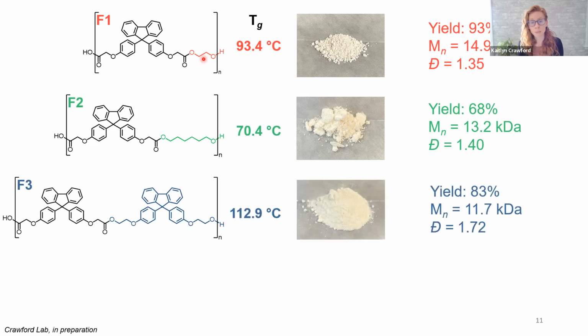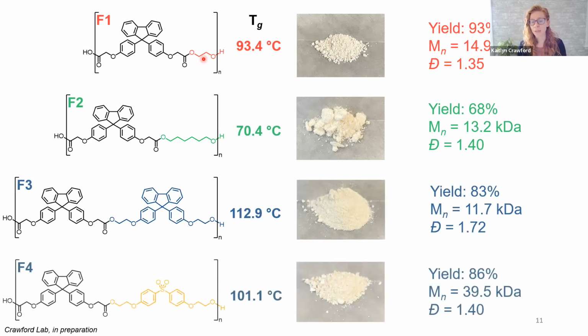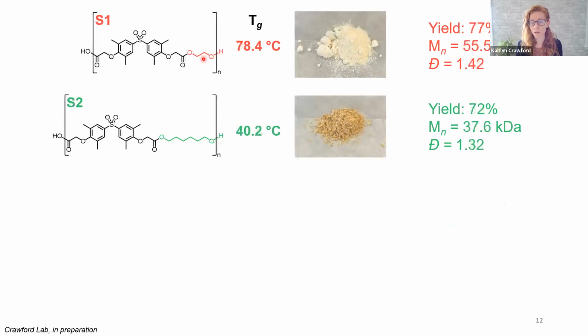We also polymerized together the fluorene diol and diacid monomers. And then we did the same thing for the fluorene diacid and the sulfone diol as well. And we did the same thing for the sulfone derivatives too. We put a short chain ethylene glycol versus the 6 diol, the 6-membered carbon diol.